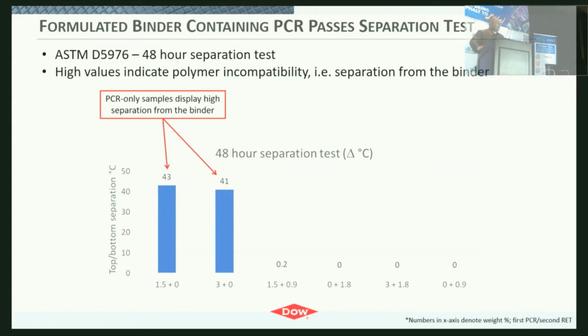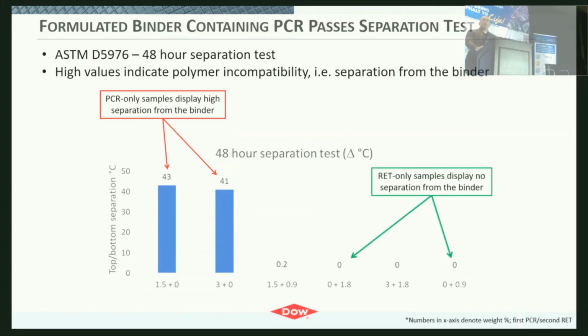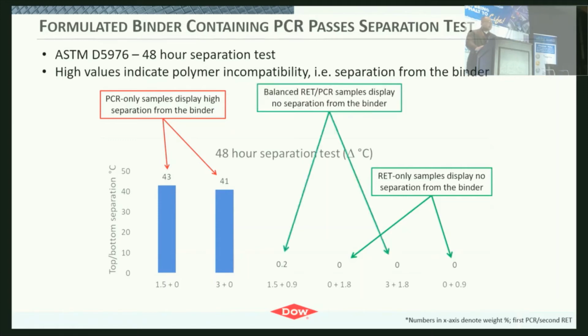And so here, the PCR samples had very high separation values. This was a low-density polyethylene that was from a clean stream, so it was exclusively that material. But you're looking at over 40 degrees C separation value. You look at the RET-only samples that were the controls, as expected at 1.8% dosage, 0.9 weight percent dosage. There's no separation. The combination of 1.5% PCR and 3% we found had no separation also. So adding the RET here did compatibilize it, and it did solve the separation using this ASTM test.